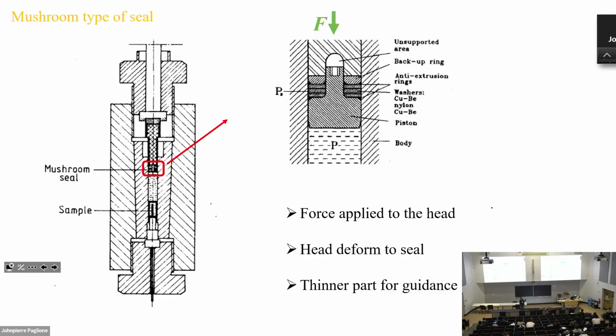There are some details to improve this that came later on. One is the so-called mushroom type of seal. The idea is, once you release the force, how can we minimize the loss of pressure? Here they use this piston that looks like a mushroom. This is what you push the piston with. Between this, you have three layers of washer: beryllium copper, then a nylon, and a beryllium copper. Then you push on this side, and here you have an unsupported area. When you push this side, the nylon, because it's soft, is going to expand. Instead of going this way, it's going to expand this way. Once it expands, you basically increase the friction between the washer and the wall. So you kind of enclose it, and the pressure will stay there.